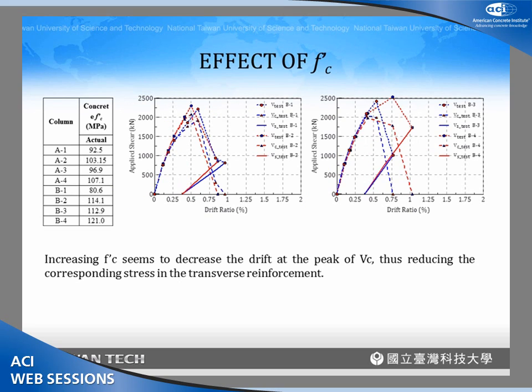This slide shows you the effect of the f'c, because we don't have very much difference in the f'c, so it's not easy to see the difference. From this test result, this one has an f'c of 80 MPa, which is the lowest one, compared to this one, which has the highest f'c.